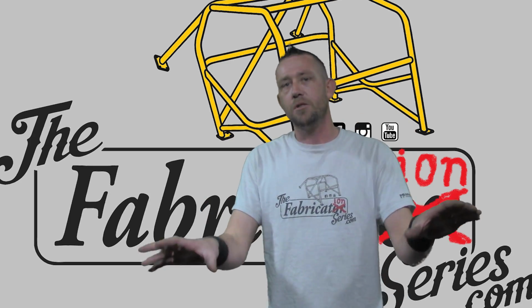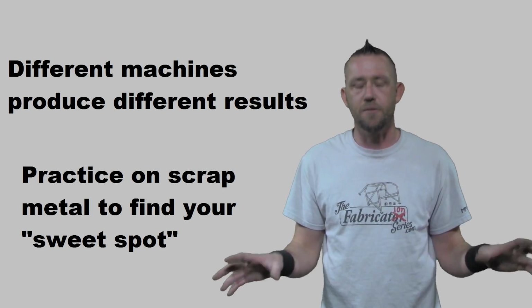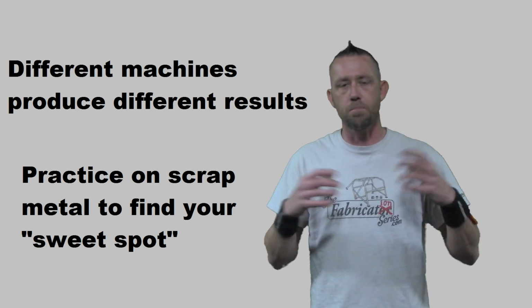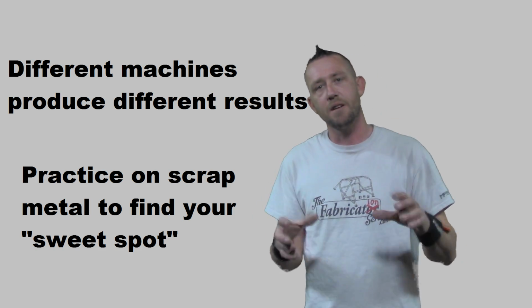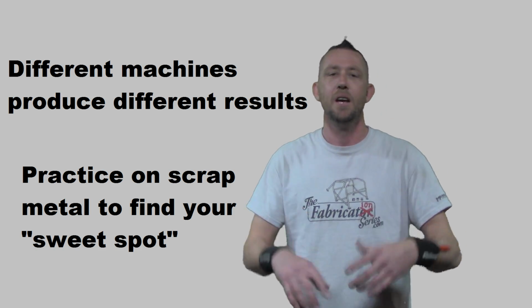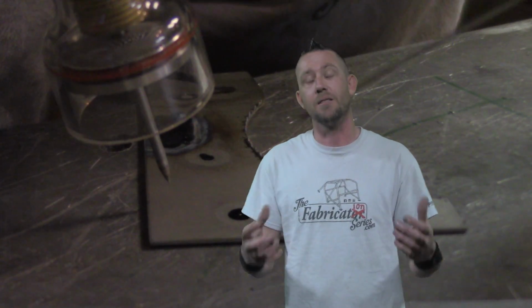Different machines are going to produce different results, different tungsten size, different tungsten grades, different everything. So it's best if you practice on some scrap metal to figure out which setting works for you. On my welder particularly, a 39 thousandths thick piece of titanium is usually best welded at 42 amps. That's my welder's sweet spot, but it's really up to you to figure out where that sweet spot is.